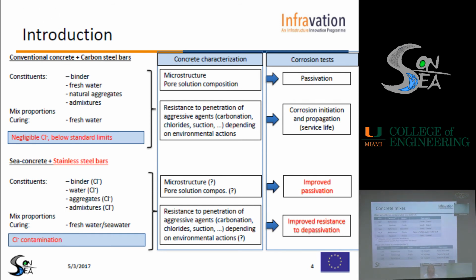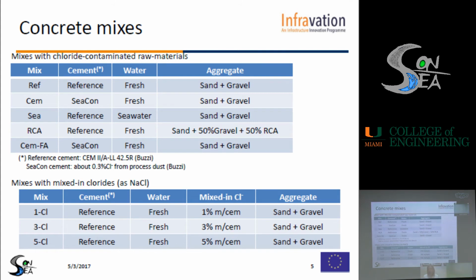Several mixes were made: a reference mix with the virgin ingredients, Cem and Cem-FA mixes where the cement was replaced with the SEACON cement that Federica Bertola talked about in her presentation. The C mix where the fresh water was replaced by seawater, and the RCA mix in which part of the coarse aggregates were replaced with recycled aggregate, which were obtained by crushing old contaminated concretes. Besides these mixes, mixes with admixed chlorides were also cast, in which the chloride content ranged from 1 to 5%